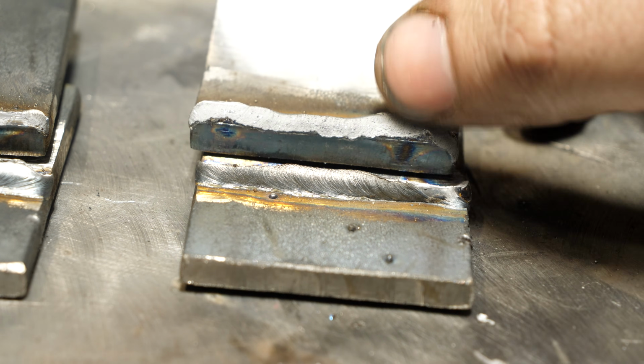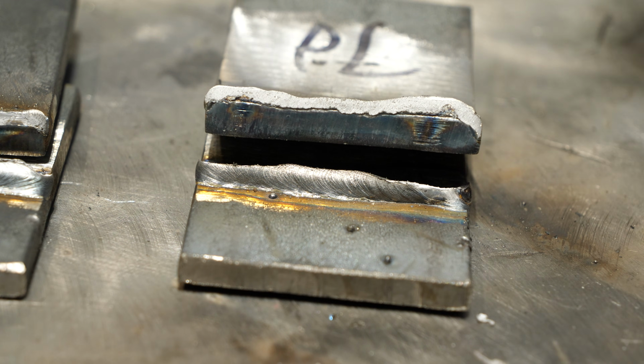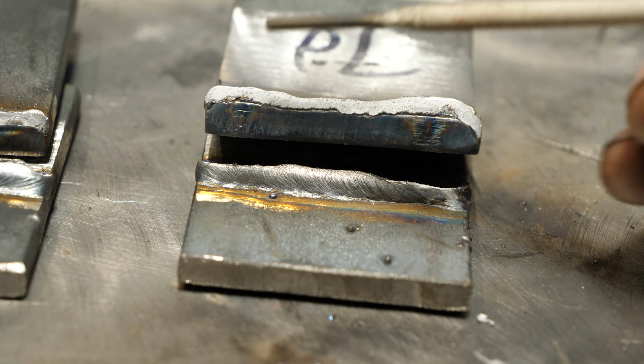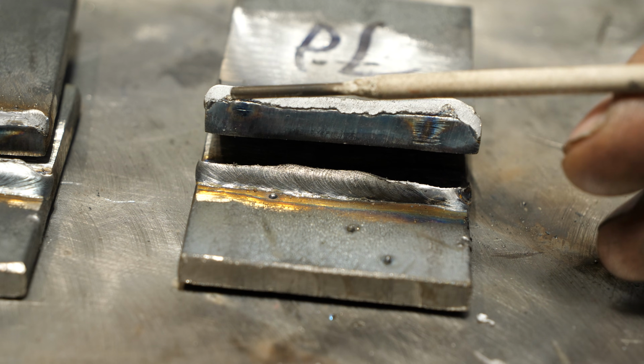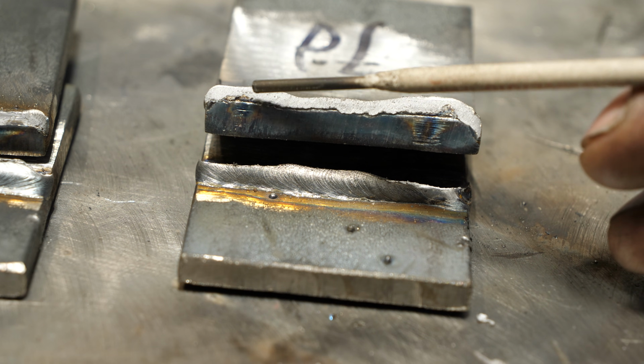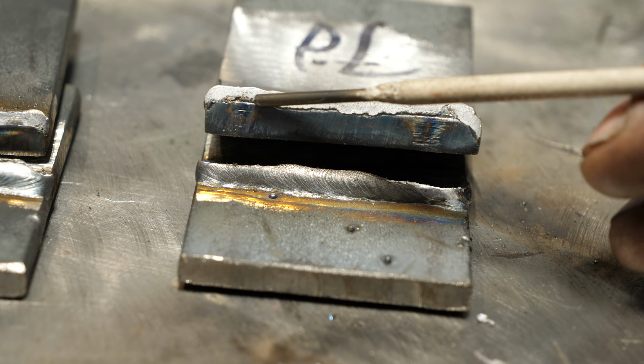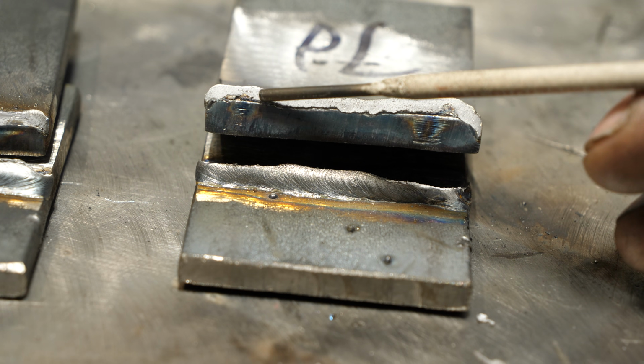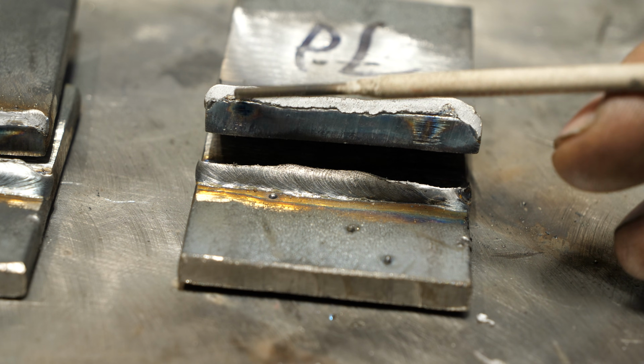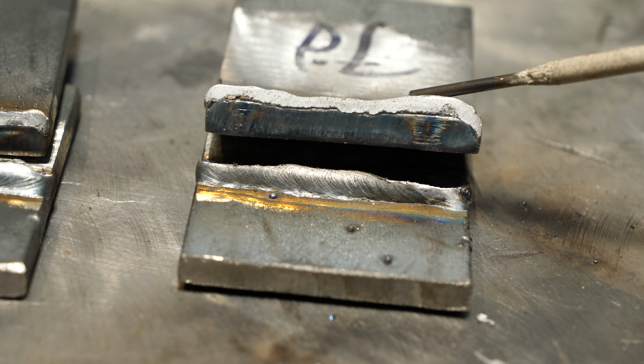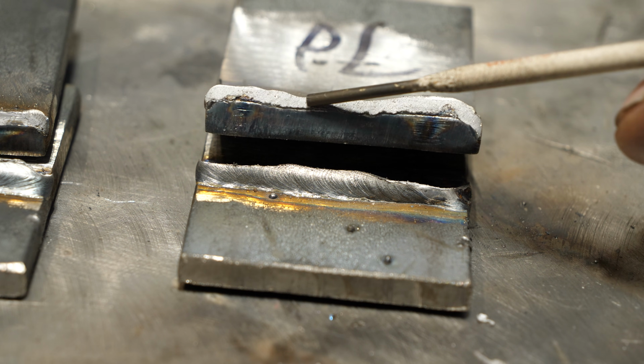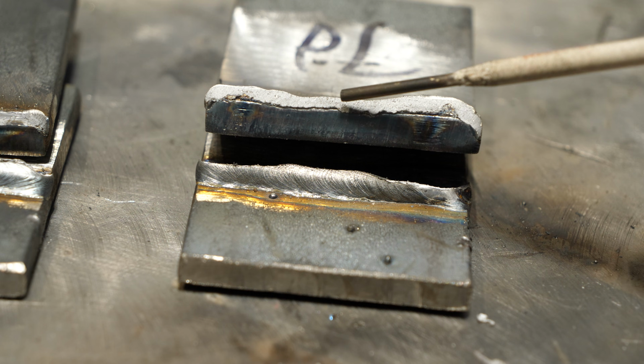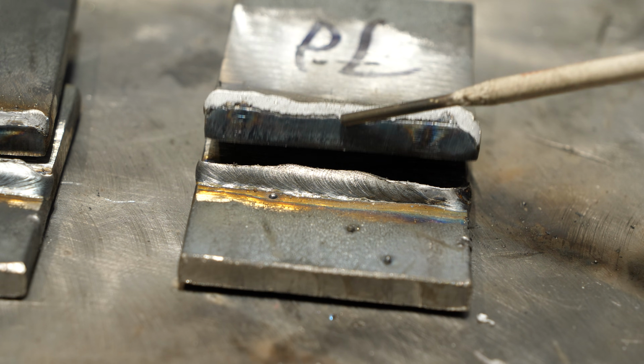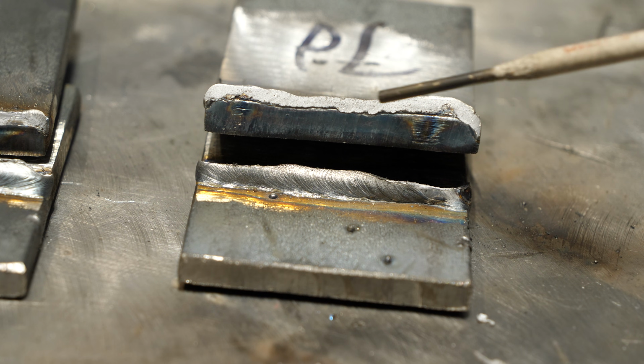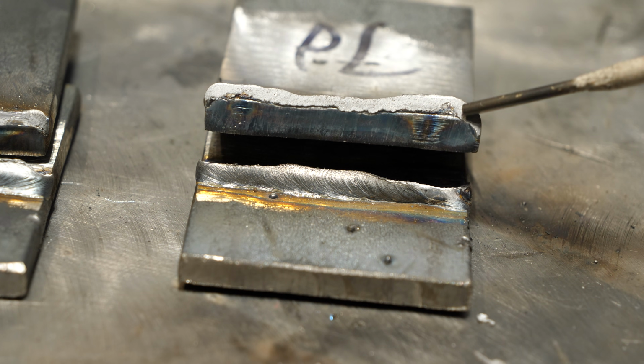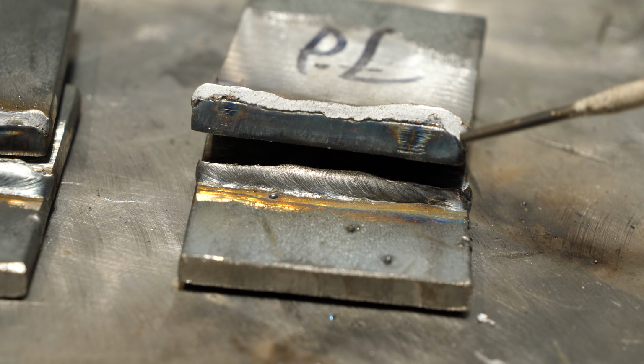Well, let's take a look at the inside of it to get some ideas as to what was going on. So when you look at the inside, we have some fusion here at the start. If you notice, it doesn't have nearly as bad of a lack of fusion within that first ½ inch. So that was a lot better than with the push angle. And then when you get down here, most of this edge is broken down, but at this section, it completely chewed through, and that's about a ½ inch section. We're looking at it up close pretty far. And then, of course, at the end, it nipped the plate and bit in here.